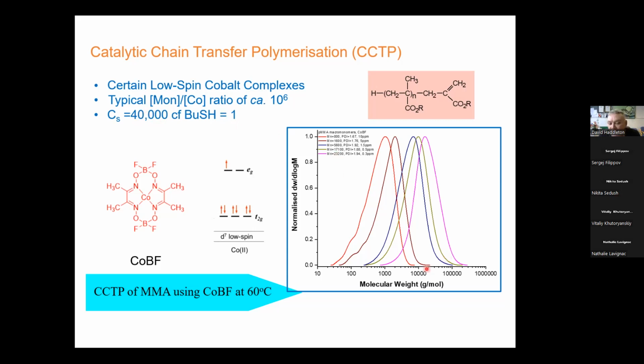And when we see the series of GPCs, we'll see with no or 0.3, cobalt will have 23,000, and by going up to 10 parts per million, we'll take that molecular weight down to 800. So this is really good for getting very small numbers of n.